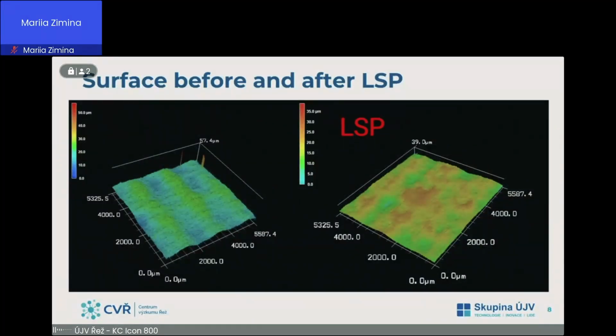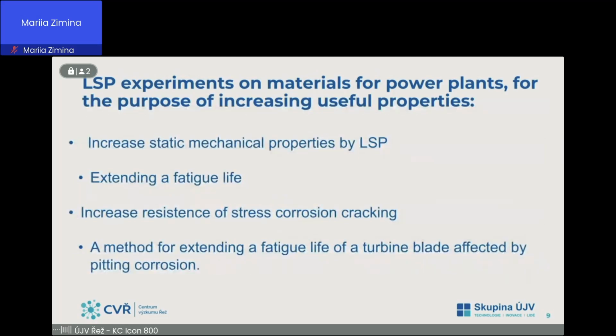There is another example of how the surface can look before and after LSP. On the left is the surface after turning, and on the right is the surface after LSP. The information is that the surface roughness can be better than before the treatment. When we use a good overlap and good setup of the LSP process, the roughness is not a problem with this treatment.